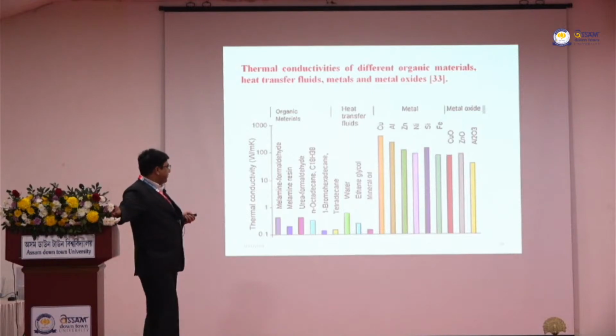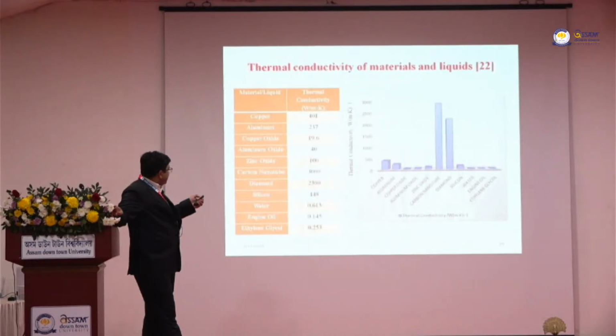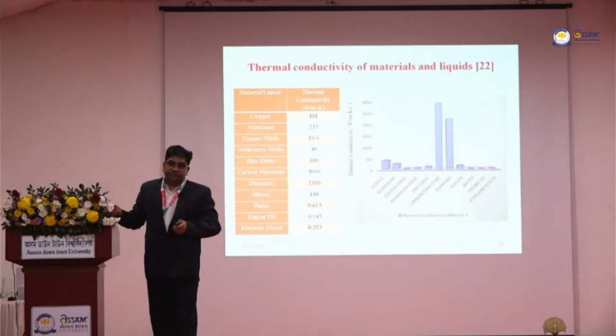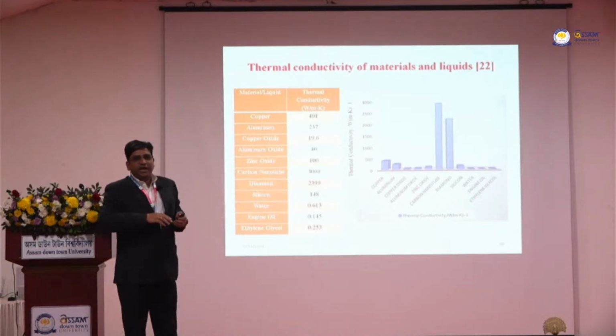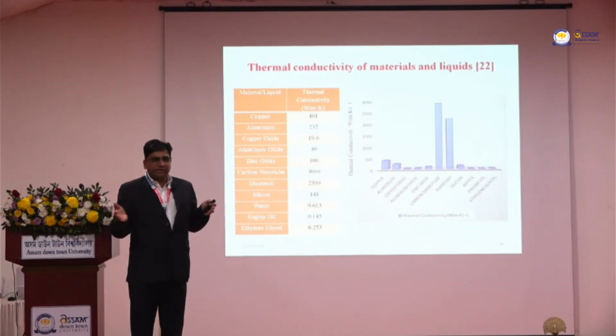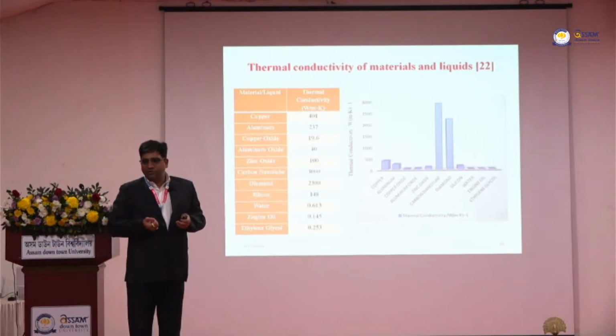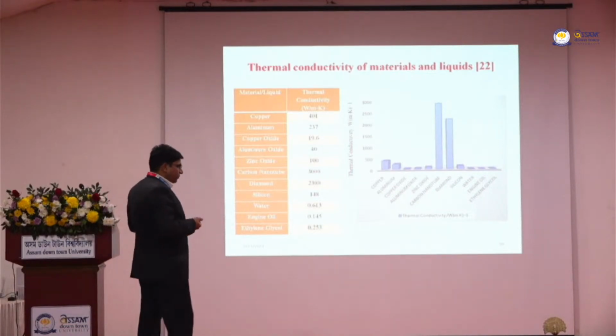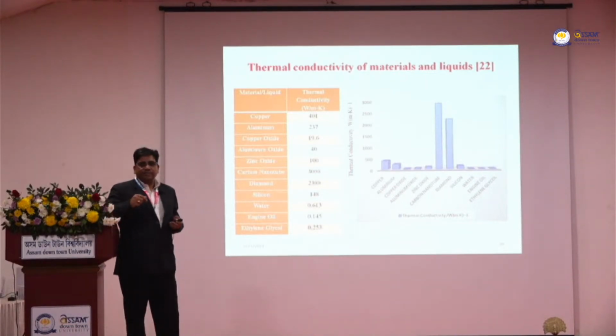So that same principle we try to use. And another, you can see here, copper, alumina and other metals have approximately more than 100 thermal conductivity value. Water is having 1 to 100 times. But if you see here, the carbon nanotubes have around 3000 times more thermal conductivity than water. So it means we have a lot of options of mixing different things to get a higher value of thermal conductivity. So what would be the benefit of doing this?